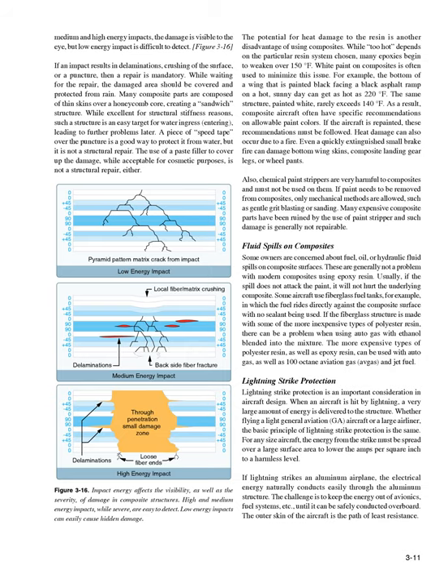If an impact results in delaminations, crushing of the surface, or a puncture, then a repair is mandatory. While waiting for the repair, the damaged area should be covered and protected from rain. Many composite parts are composed of thin skins over a honeycomb core, creating a sandwich structure. While excellent for structural stiffness reasons, such a structure is an easy target for water ingress, leading to further problems later. A piece of speed tape over the puncture is a good way to protect it from water, but it is not a structural repair. The use of a paste filler to cover up the damage, while acceptable for cosmetic purposes, is not a structural repair either.